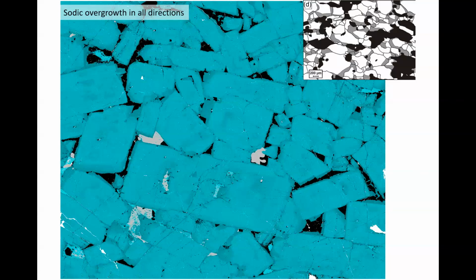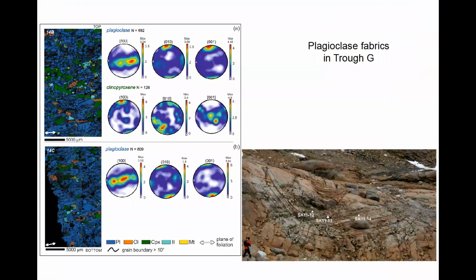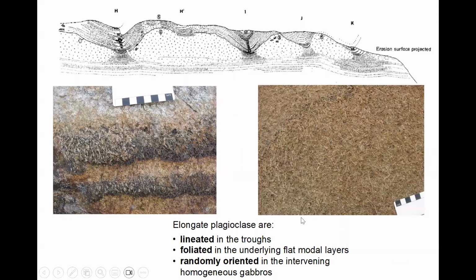We haven't got any evidence of dissolution and reprecipitation. There's no deformation that would be indicative of viscous compaction. Or this black stuff here is quartz, which we'll get back to. Okay, so the microstructures say no compaction. There is, however, a very strong fabric in these troughs. So this is looking down the axis of one of the troughs here. And this is a paper that Stoyevich and I worked on some years ago now. And there's a very strong lineation of the plagioclase and apatite as well, and olivine, parallel to the troughs. Now, it has been suggested that this lineation is due to some sort of shearing during compaction, but that also can't be the case.